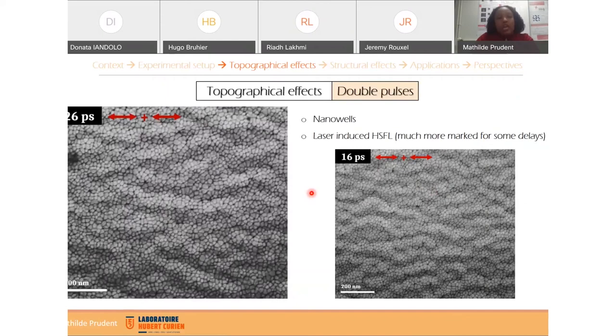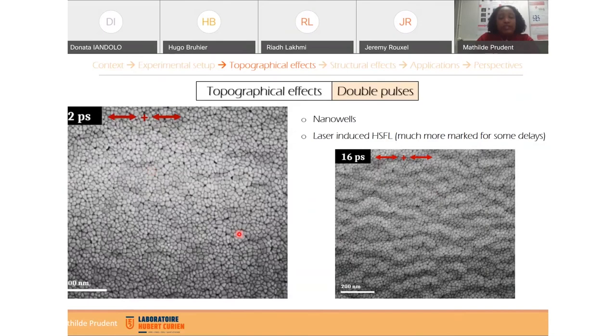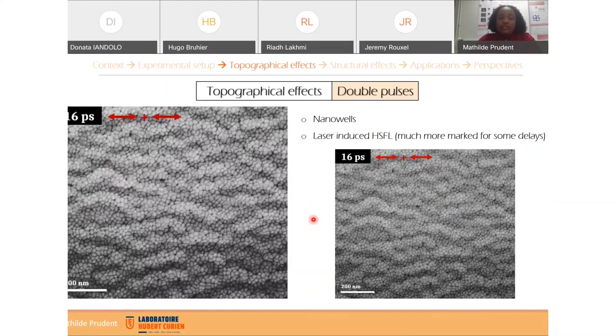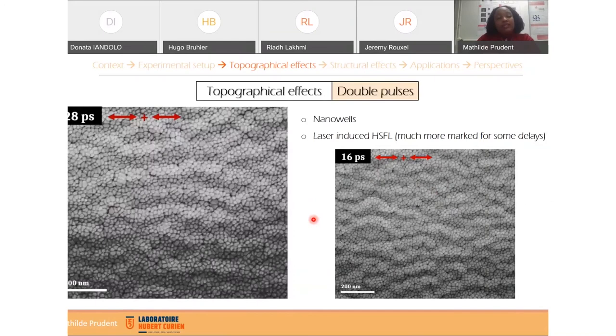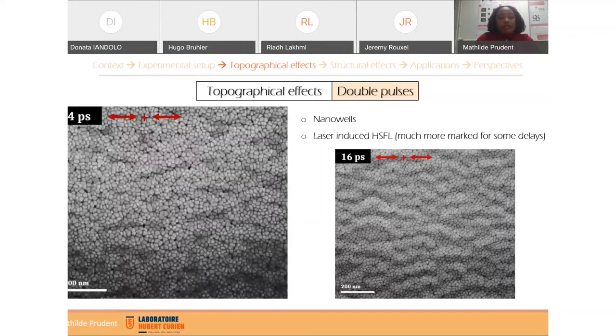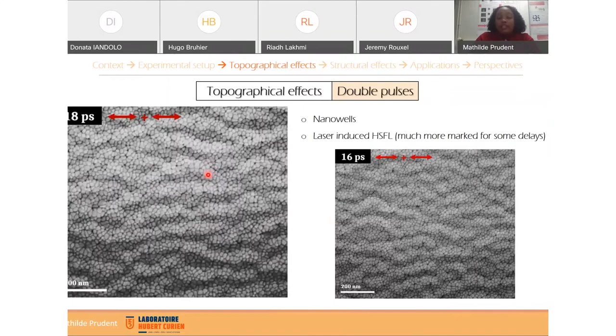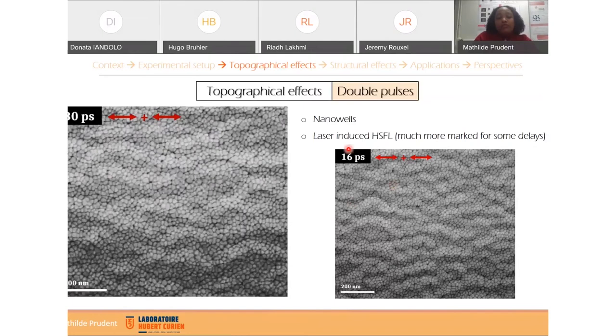We can see that, like before, we have nanowells in the irradiated sample. But we also create HSFLs, so high spatial frequency LIPSS, and we can see that they are much more marked for some delays. For example, starting from 2 picoseconds until 30 picoseconds, we have this HSFL, and visually they are much more marked for the delay of 16 picoseconds.